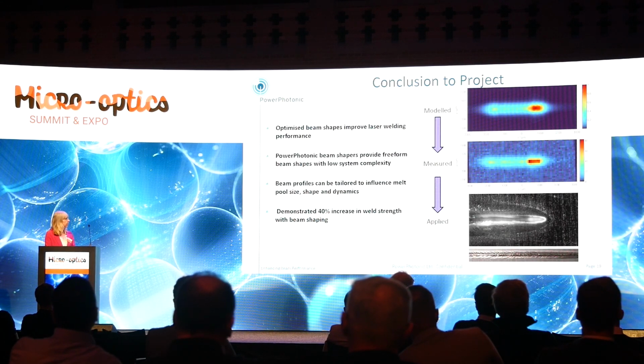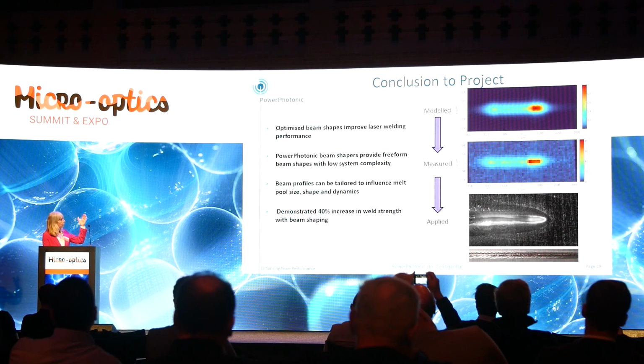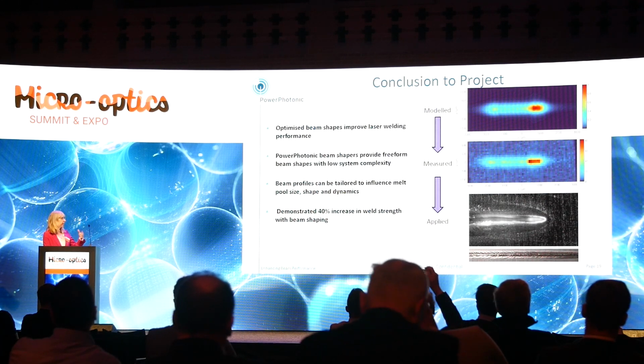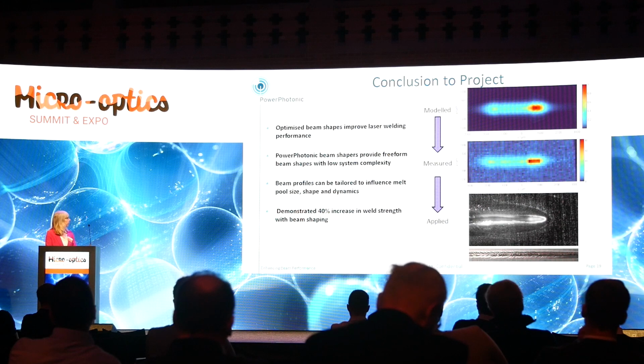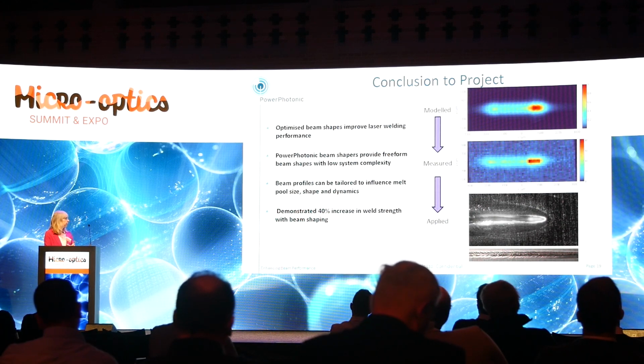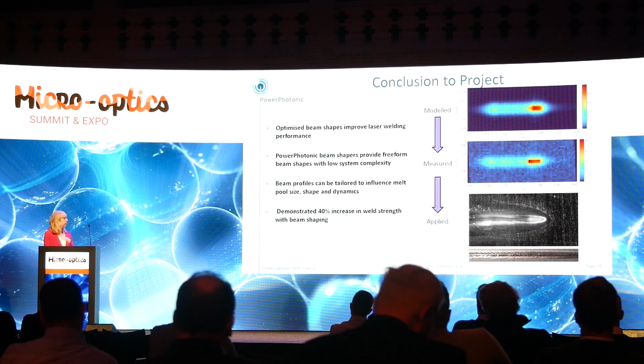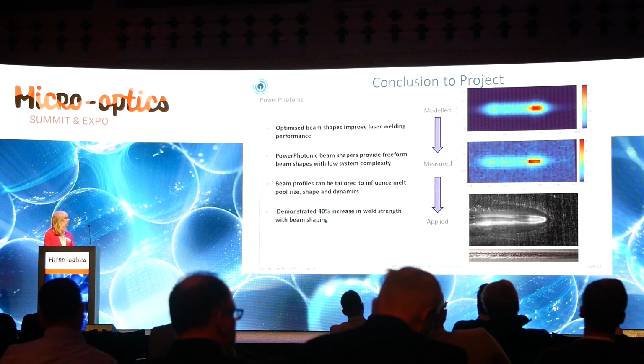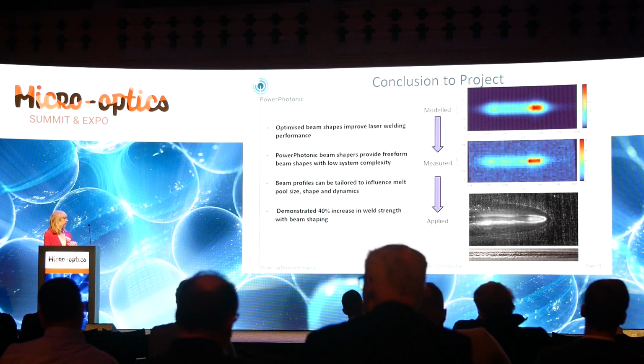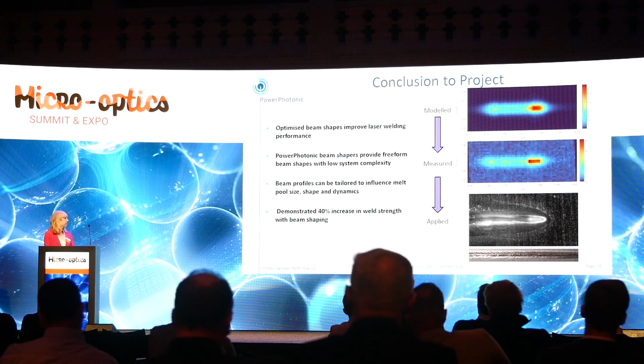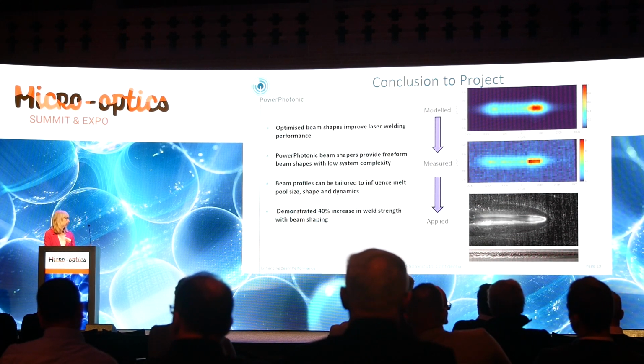The conclusion to the project that was carried out is that beam shaping did optimise the laser welding performance. You can see here that our model and the measured were very similar, and then the applied also. PowerPhotonic beam shapers provide a freeform beam shape, so we can change what the beam shape looks like, and we can change what we want. As I said, they're all customizable. Beam profiles can be tailored to influence the melt pool size and shape and dynamics, and very happily we demonstrated a 40% increase in the weld strength with the beam shape.